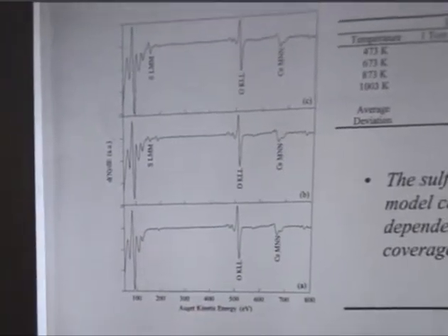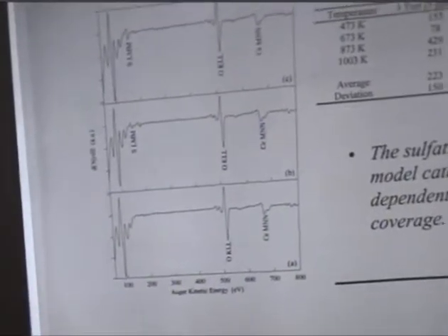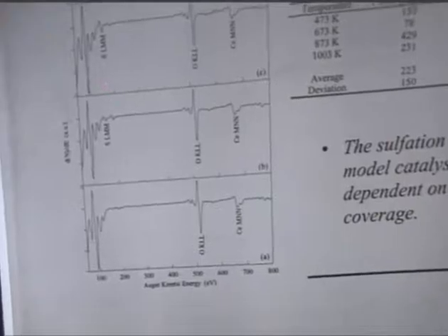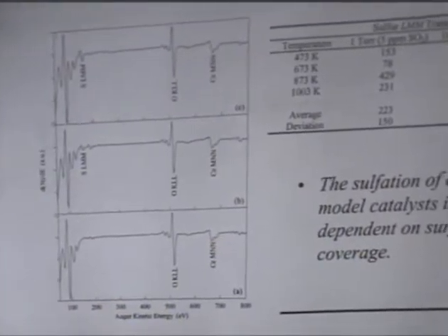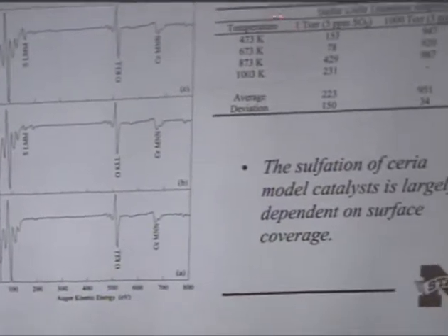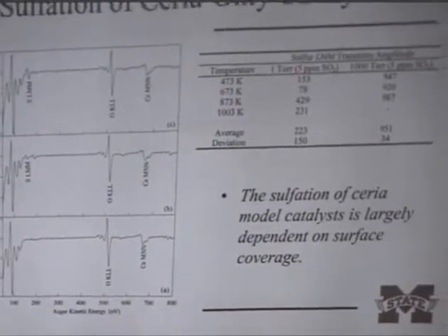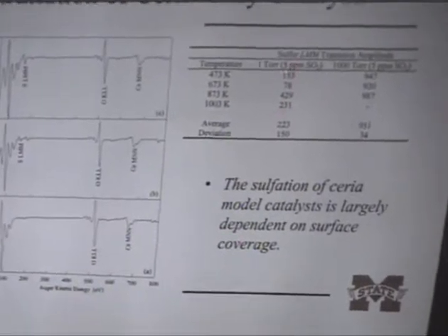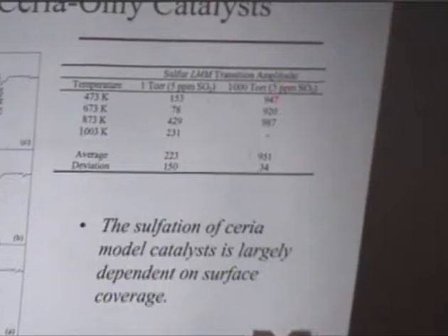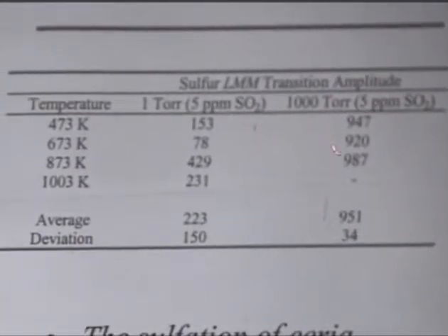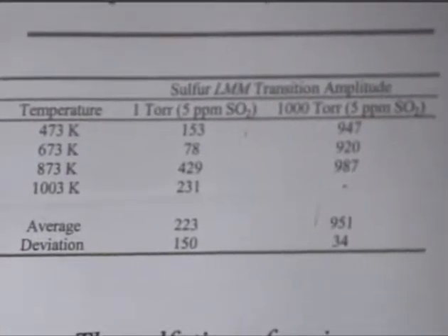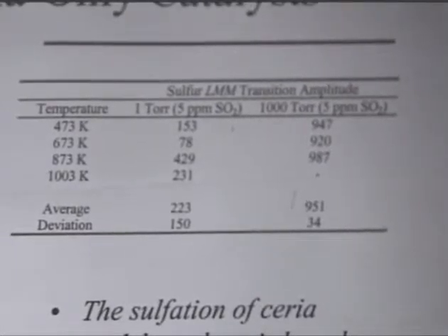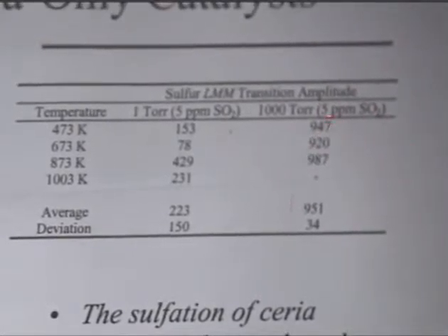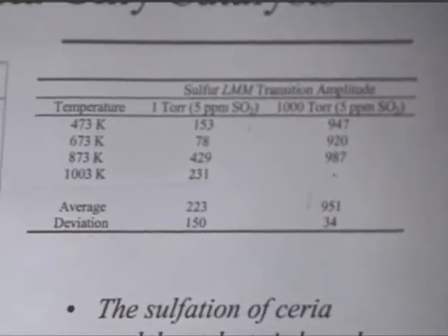So when we show the results that we got with the mixed metal oxides, it took a lot of numerical jockeying to be able to extract those signals out. But anyway, with 100% ceria, what do we see? Well, we look at these different temperatures, and this is just simply the integrated area of our Auger transition. And the first one we see is at higher pressures here, which we think corresponds to essentially a monolayer of coverage. We do not see a difference in coverage as a function of temperature.